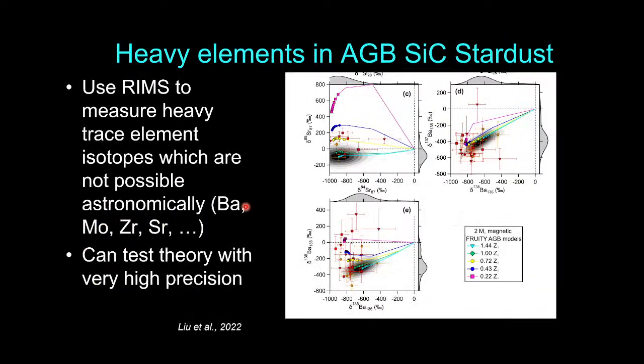And this is just another example, like I had of the oxide grains, of how we can compare specific stellar models to the grains that have different parameters of the models. And the stellar modelers really love this because it helps us better understand how these stars evolve, because there's still a lot of uncertainty in the details of how stars evolve, especially in these complicated later stages like AGB, of how material gets mixed between different shells, how convection works, what the exact temperatures and pressures are, which goes into the nuclear physics. So these grains provide snapshots of actual stars that the models can be tied to. So very, very valuable for testing theory with very high precision.